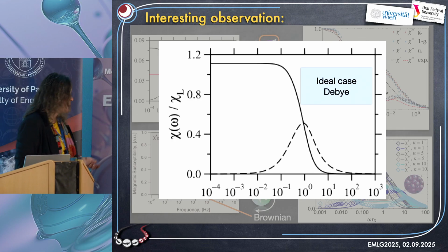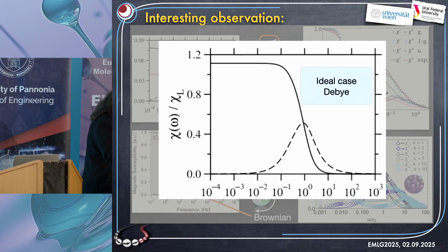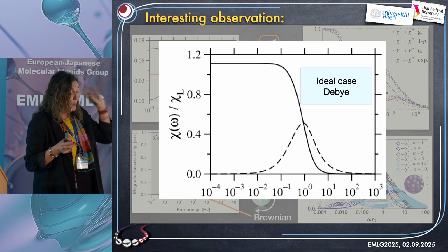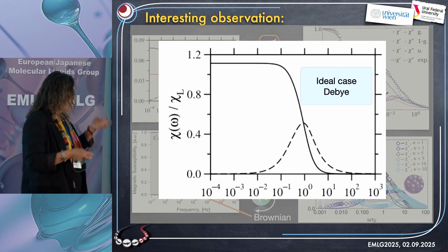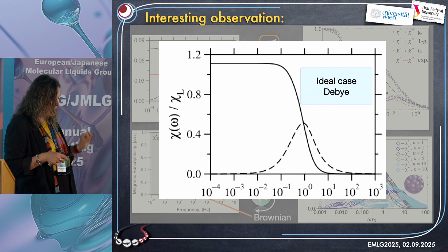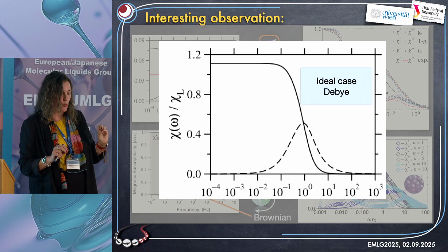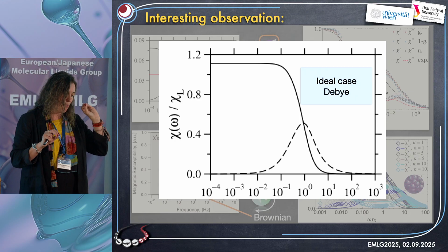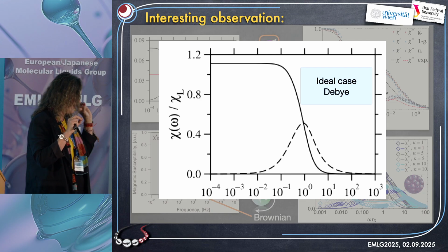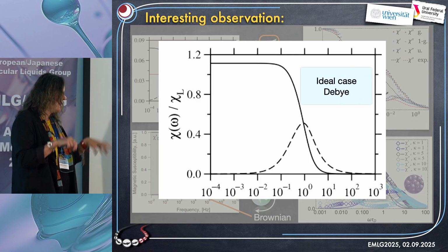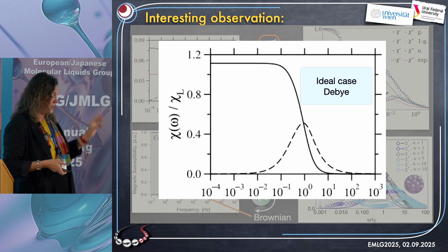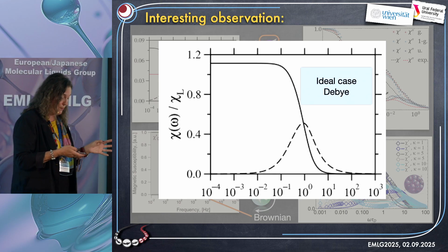So I'm wrapping up. What did we see? I remind you, where did we start? We started with the aim that we want these magnetic particles of some kind to actually heat. For that, we need full control over not only the position, but also the height of the maximum of the imaginary part of the dynamic susceptibility, because that is what gives you the heat production.